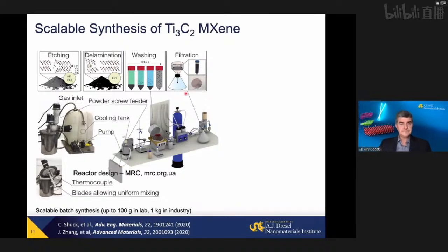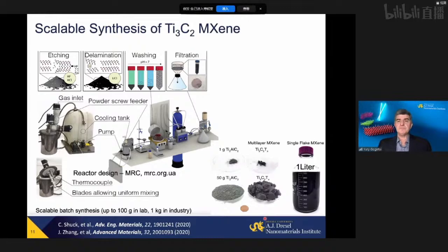There's also one more important feature of those materials. There are more than 200 two-dimensional materials which have been reported. Only a handful of those can be made in any significant amounts: graphene, molybdenum disulfide, boron nitride, some oxides here. MXenes are produced by wet chemical etching from ceramic precursors, MAX phases. This is a reactor which was designed by the Materials Research Center in Ukraine for us. We have a couple of reactors of different volumes. We can make up to 100 grams per batch. In industry, there are reactors already capable of making a kilogram per batch. Fundamentally, it should be possible to make a ton of material per single run in a reactor.